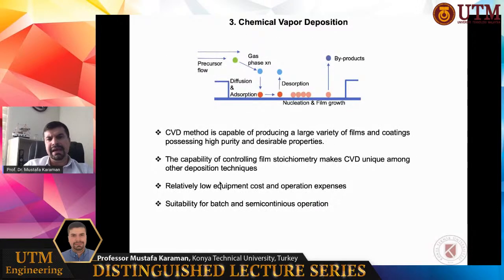Here you can see the mechanism of chemical vapor deposition: precursor flow, some gas phase reactions, diffusion, adsorption on the surface, desorption, nucleation, and film growth. So, it is a very complex process, and the chemical rate is determined from the combination of these steps.